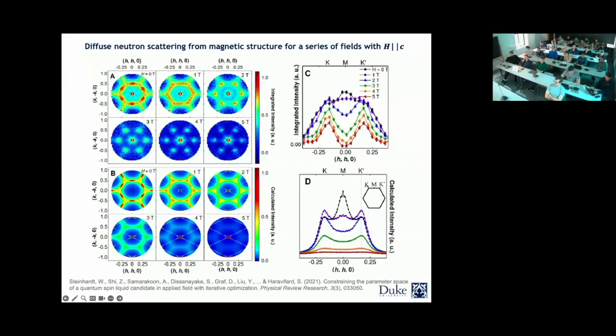When we collected this data, we got in touch with Christian Batista's group, which was working on triangular lattices. We mentioned that this is what we are seeing, and this has not been seen before. Whatever model we predict for the zero field also needs to follow this rule that when you start to apply the field, it needs to have this phase crossover between the M point and the K point. This is what they have done through iterations and classical and quantum Monte Carlo simulations.